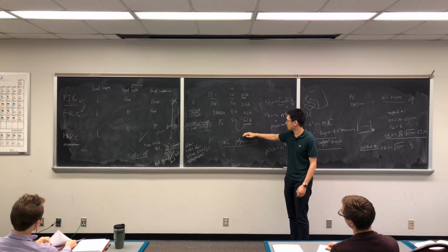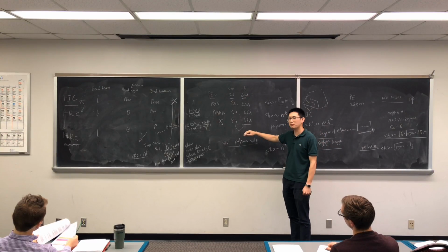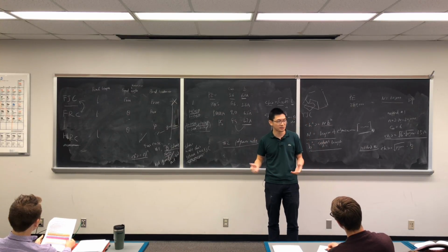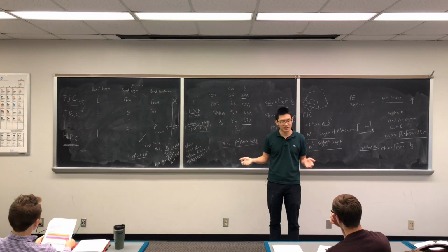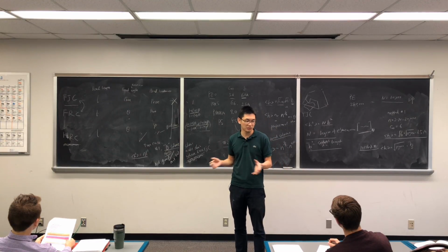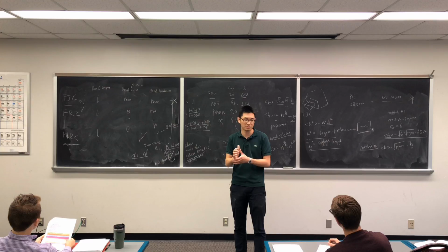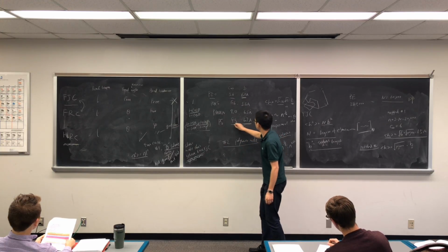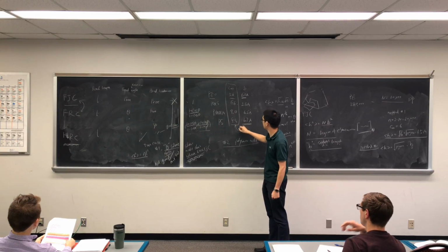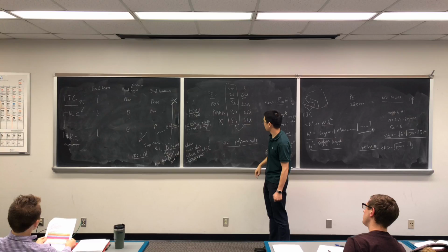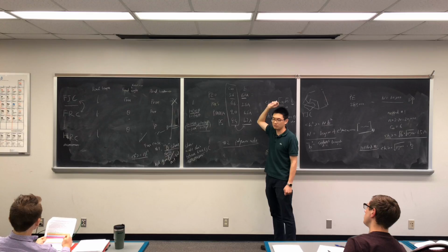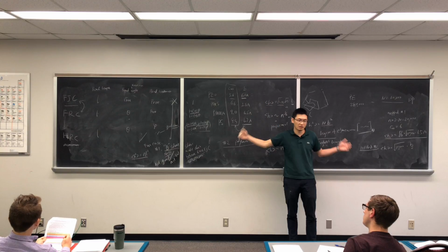We talked a little bit about the real-world values of the characteristic ratio. You want to memorize that it's somewhere less than 10 for most polymers. Of course, super rigid polymers will go above 10, but most commodity polymers are semi-flexible. You can use C infinity to describe it, or an equally important term, the segment length b, where you can calculate b and use the degree of polymerization times b squared to count how long or how big your chain is.